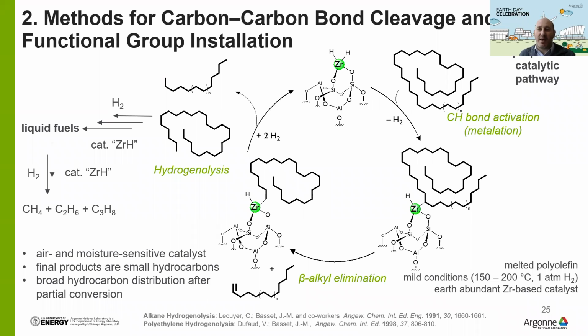But I want to go back a little bit. I'm a chemist. I really like to understand how catalysts and how processes work. I showed before, for example, nanoparticles that can do the hydrogenolysis of carbon-carbon bonds. There are also examples of single site or isolated cations on surfaces that catalyze the cleavage of carbon-carbon bonds using hydrogen. The difference between this kind of catalyst and the nanoparticles is that using these cations on surfaces, the final product is 100% gases, because these are very, very efficient, and they keep cleaving carbon-carbon bonds up to methane, ethane, and propane.